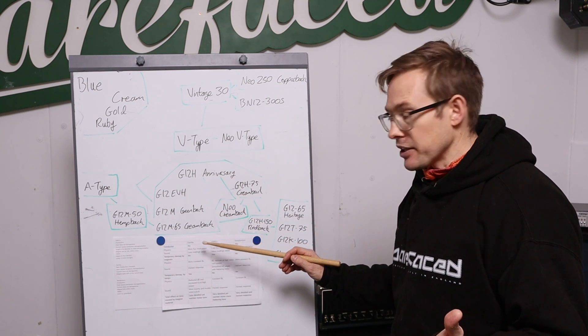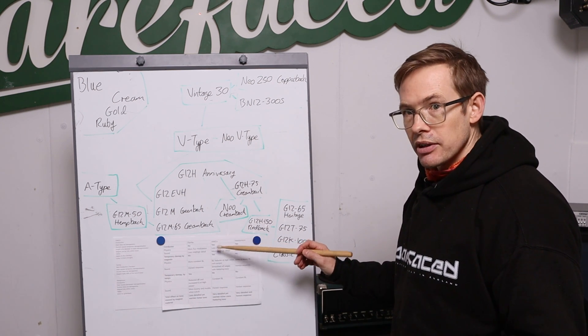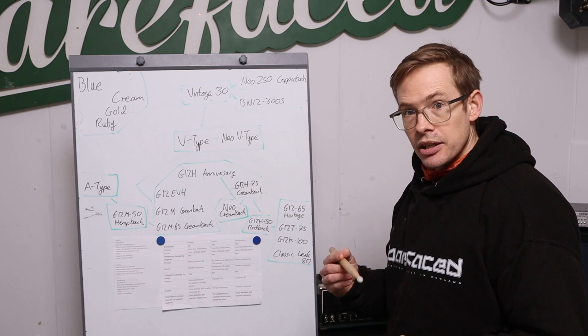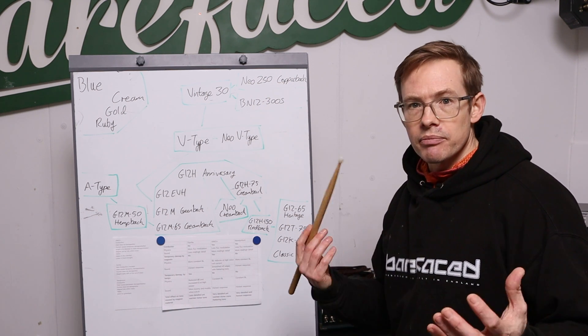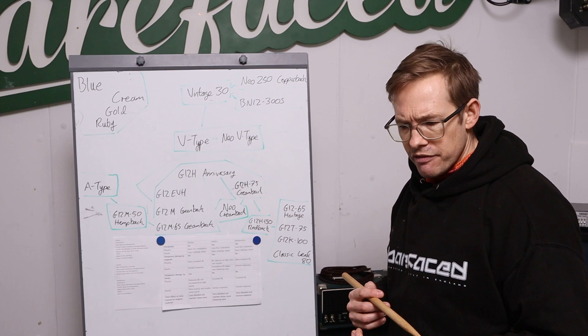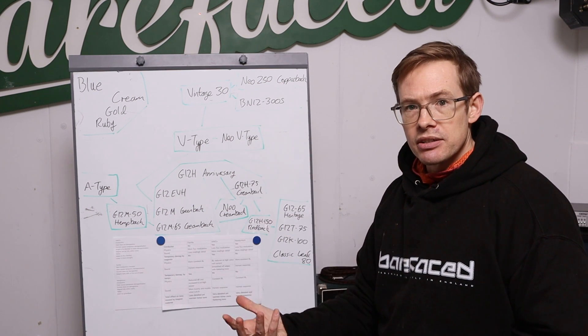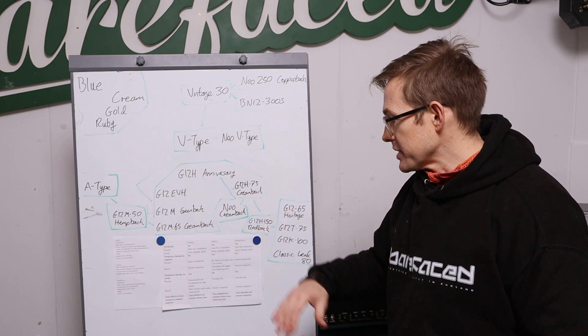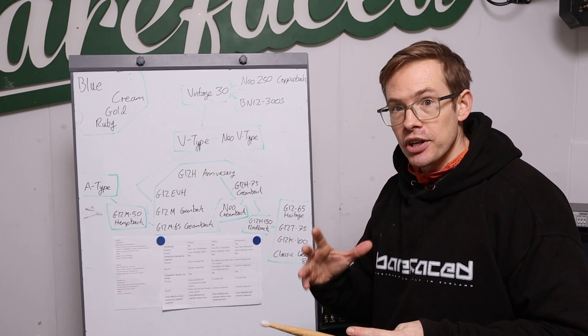The difference between the ferrite magnet and the Alnico and the neo magnets: Alnico is an alloy of aluminium, nickel, and cobalt. A neo magnet is actually an alloy of neodymium, iron, and boron — so it's not really a 'neo' magnet, it's an NdFeB magnet. Ferrite magnets, however, are — iron ferrite, strontium ferrite — basically a powder of various iron-related magnetic materials suspended in a clay to make a ceramic. The key thing about that is it's clay ceramics; they do not conduct electricity — like porcelain — it's non-conductive, it's an insulator.